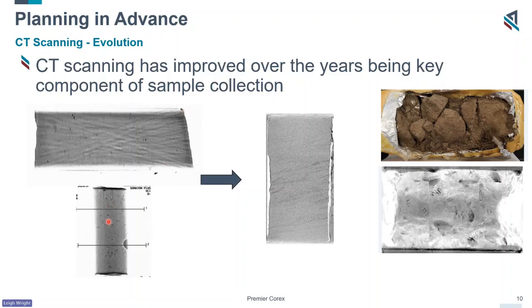Now, in the pilot scan here, you can see where cross sections have been taken. I've left them out of the slide, but you can see that there's features throughout the sample. But when you're looking at the slice through here, you've got saltire, which is a nod to Scotland, but unfortunately it's not suitable. It's masking the bedding and small features. You can see higher density areas where the colors flipped here, but you're having to rely on having visual eyeballs on the sample when the sample's opened and looked at, because you can't see any fabric really to a high level to look into the plugging zones.